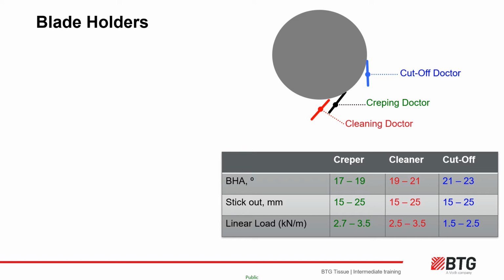Each blade sits in its own blade holder, which is set up to make a specific contact angle or blade holder angle with the Yankee tangent. If this angle is too low, the sheet takeoff can be compromised. Too high, and the blade can be too aggressive against the coating and cylinder and potentially cause chatter and damage. Usually the creper has the lowest blade holder angle, enough to cut through the sheet and crepe with good sheet control, but not too high an angle so that it induces chatter. The cleaner blade holder angle is usually higher and the cut-off angle higher still to ensure efficient cutting through the sheet.